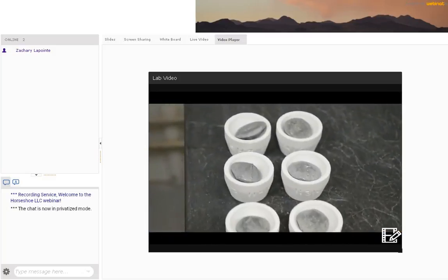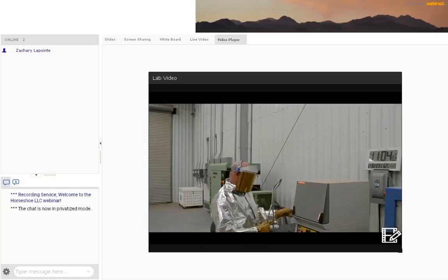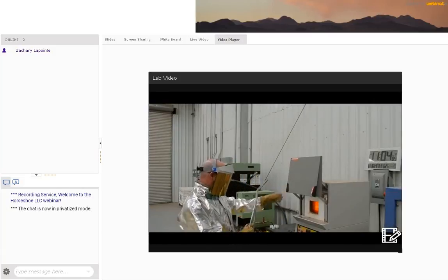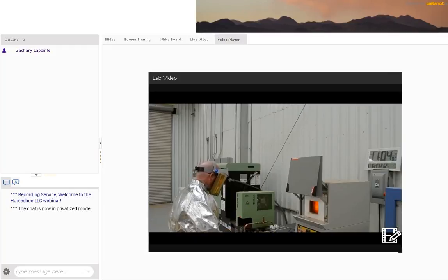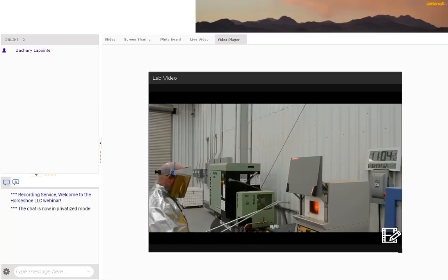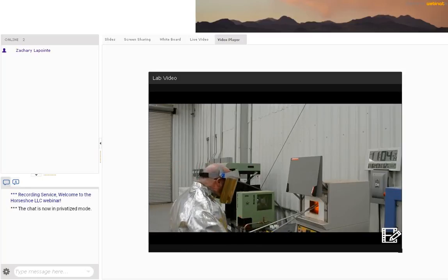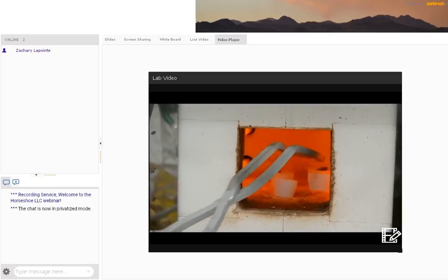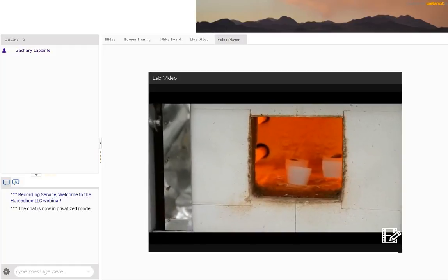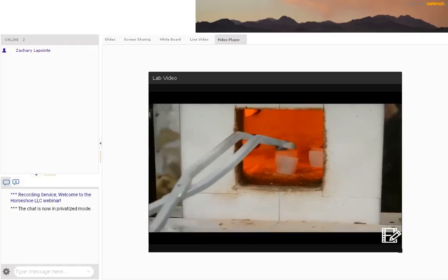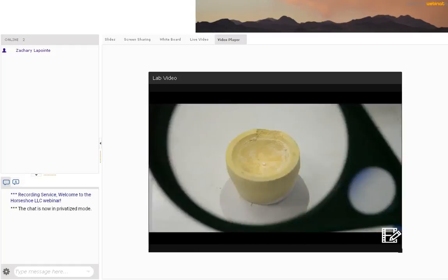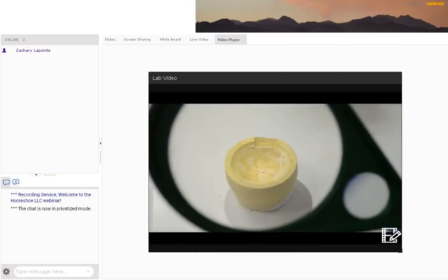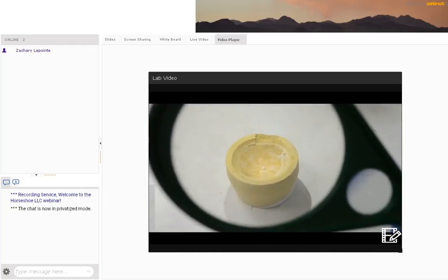The lead buttons are then placed into bone ash cupels and loaded back into the furnace at 870 degrees Celsius. This oxidizes the lead and reveals the precious metal. The bead that we're looking for will be shown here in just one moment. Here you can see cupels coming out of the oven, and this is where we will identify the small bead. These beads are gold and silver.